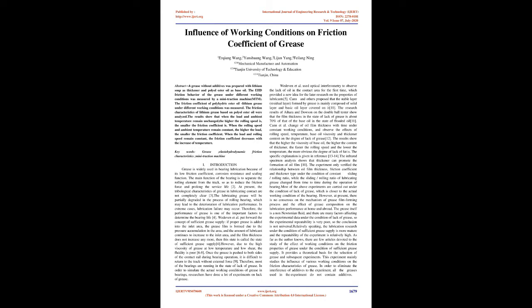The results show that when the load and ambient temperature remain unchanged, the higher the rolling speed is, the smaller the friction coefficient is. When the rolling speed and ambient temperature remain constant, the higher the load, the smaller the friction coefficient. When the load and rolling speed remain constant, the friction coefficient decreases with the increase of temperature. Keywords: grease, elastohydrodynamic friction characteristics, mini-traction machine.